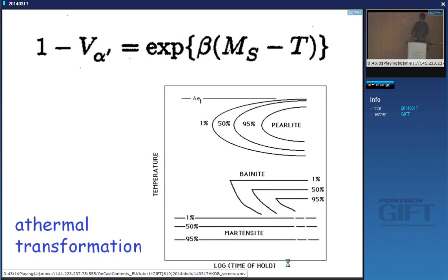Okay. Someone mentioned that martensite forms by rapid cooling. Now that isn't strictly true either. If I add 38% of nickel to my alloy, then I can cool very slowly down to cryogenic temperature and I will get martensite. So it all depends on the hardenability of your steel. I can change this time temperature transformation diagram by adding alloying additions. I can cool very, very slowly and get martensite, but in some cases I will need to cool very rapidly to avoid other transformations. Okay?